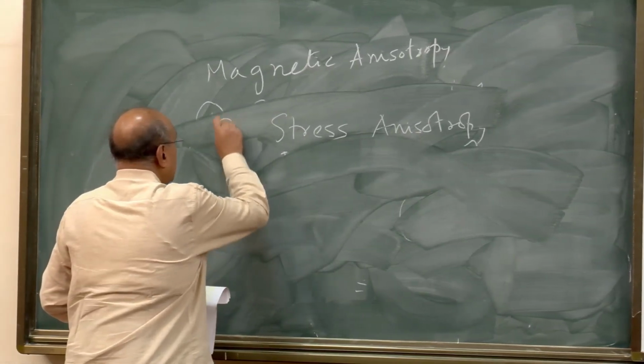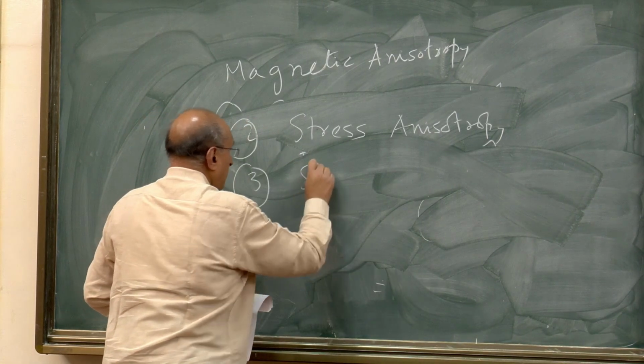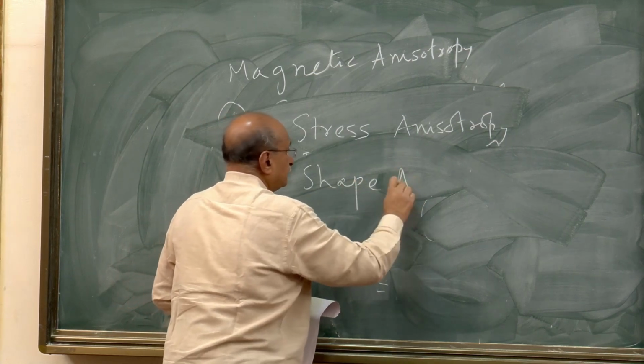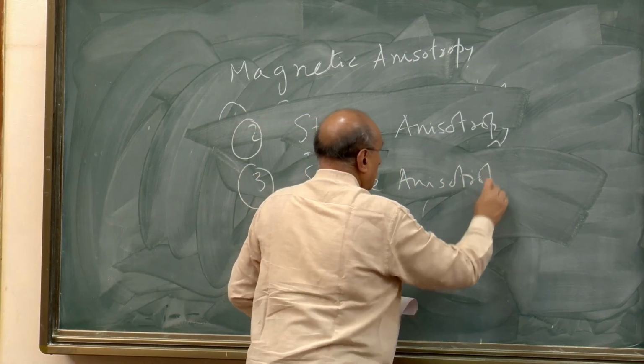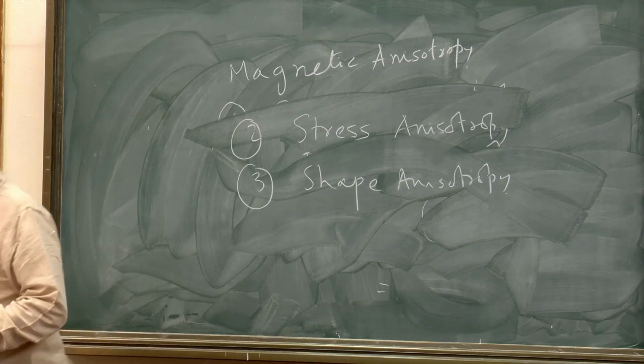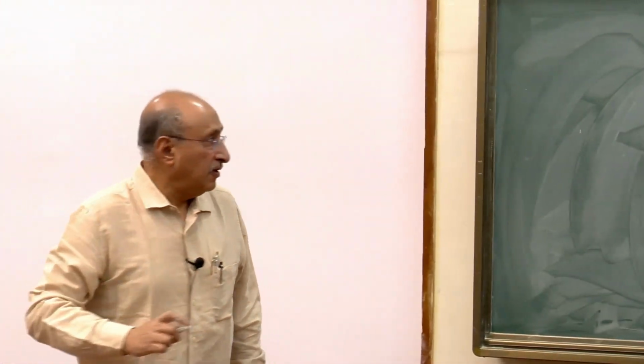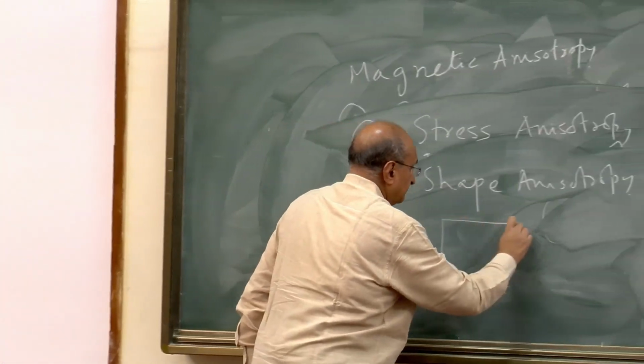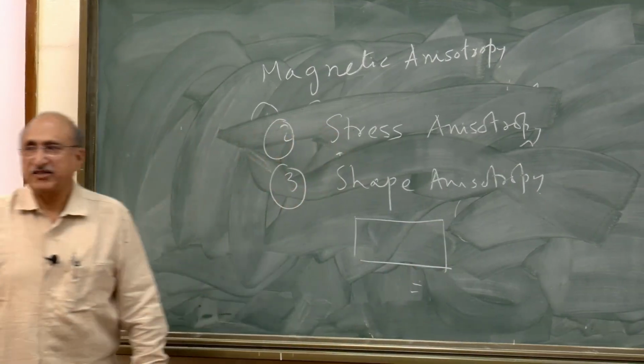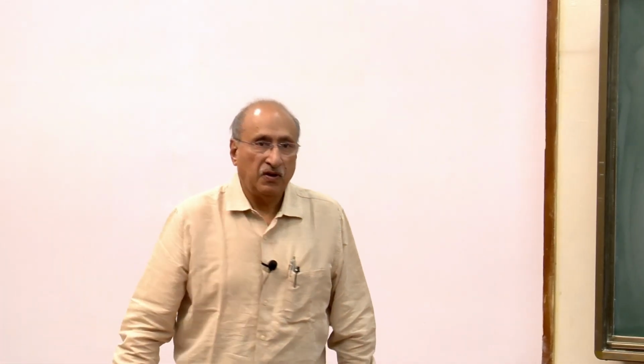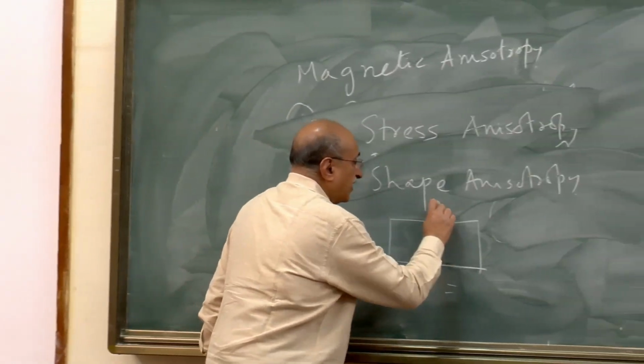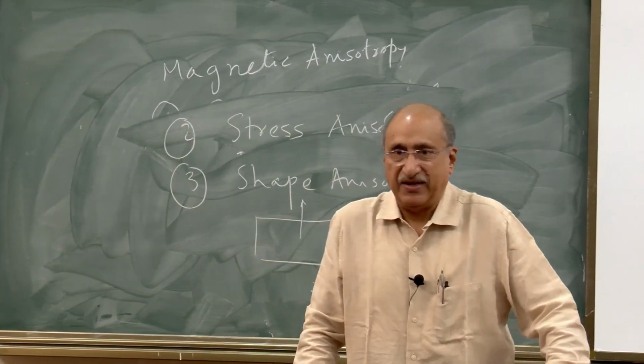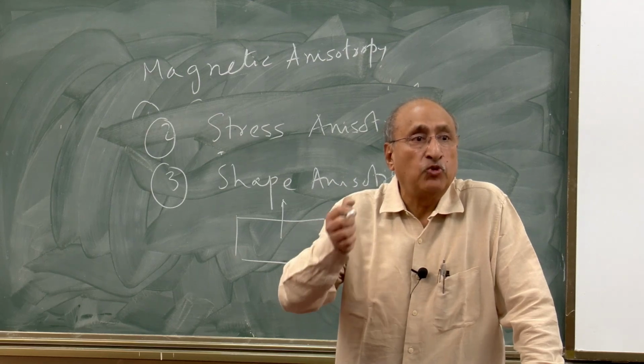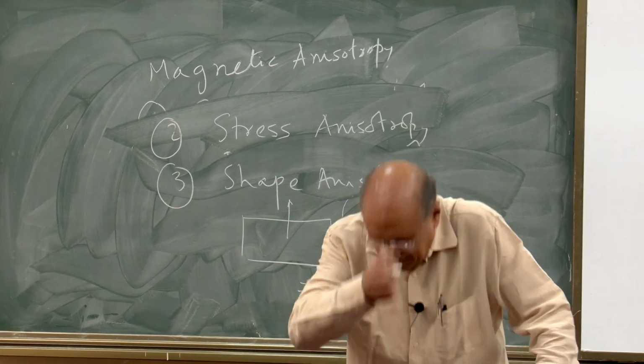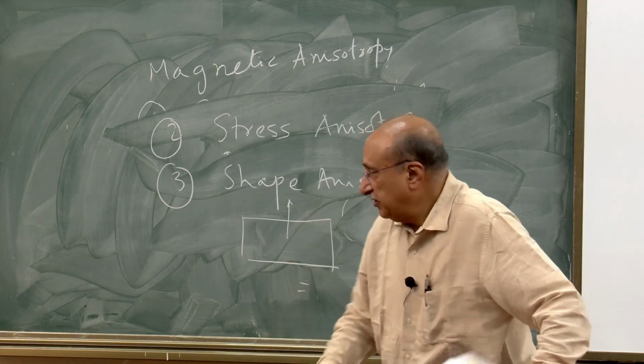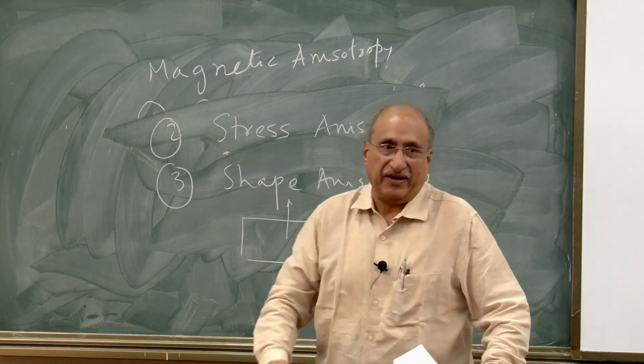The third thing is shape anisotropy. This is related to the magnetostatic field. If you have a material like this, let's say a thin film, and you want to magnetize it in this direction, normal to the film, it will be difficult to magnetize, because the poles that you are going to create will be too near to each other. If you magnetize it in the plane, it's much easier to magnetize, just because of the shape.